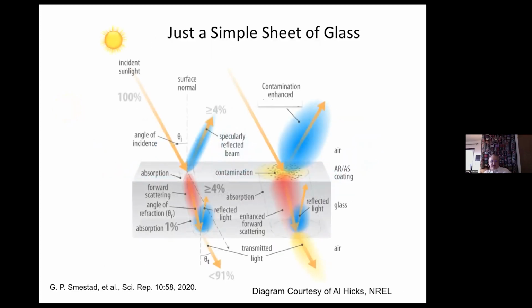Now I show you this same kind of thing applied first in the case where you don't have particles on the surface. This is a clean part of the glass. On the right-hand side, we have the dirty glass, the soiled glass, as you can see, this contamination or soiling. You have the incident light coming in at some angle, theta sub I. Normally, if you don't have an anti-reflection coating, you have something like 4% surface reflection. You have some amount of forward scattering, and then coming through the glass, you again have first some absorption, and then another 4% reflected, 91% is coming out.